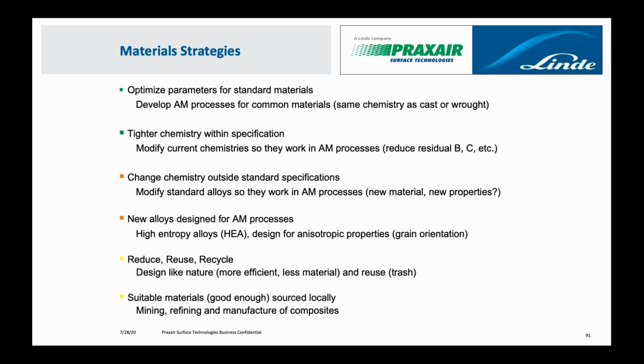Sometimes some other alloys may be a little more difficult. If you think about materials that are difficult to weld, those may not be the best materials to use for additive manufacturing. But sometimes you can get some of the benefits by modifying those chemistries or tweaking. Some of the initial things you might do is reduce the boron content or the carbon content. Those are some of the things that might make these brittle, or might cause some segregation or cracks when they solidify.